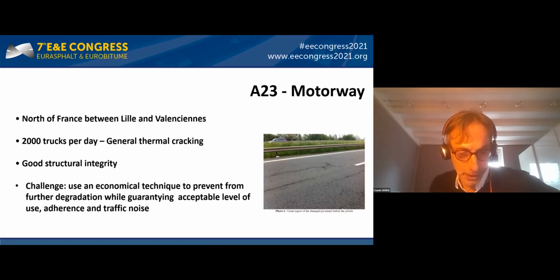The use of combined layers coatings has also been validated on highways, as it happened on the A23 highway, for instance, in the north of France between Lille and Valenciennes. The average daily traffic was greater than 2,000 trucks per day. It was a semi-rigid structure covered with a 14 centimeter thick bituminous product and a wearing course dating from 2004 consisting of a thick 0/10 millimeter bituminous mix designed with a multigrade binder for a total thickness of 7 centimeters. The roadway has a state of generalized thermal cracking with locally an aggravation of the surface degradation, but the structural integrity of the pavement was good. The job site took place in 2013.